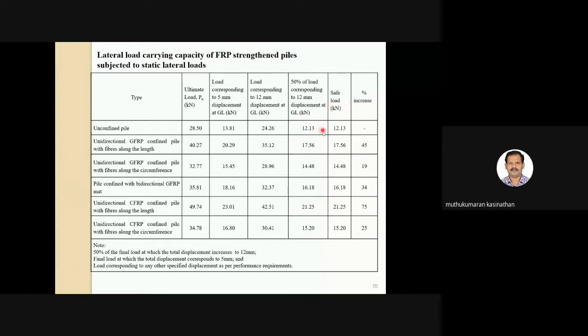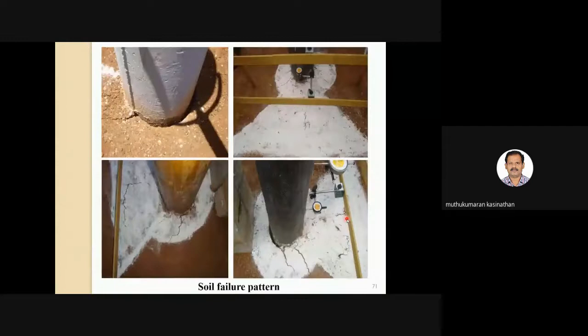So accordingly, the pile capacity has been estimated. So you can see here the variation of increment in the pile capacity, irrespective of the type of FRP. Minimum, you are getting almost close to 20% enhancement if you are using carbon fiber with the parallel arrangement. With the perpendicular arrangement, that is the longitudinal arrangement, you are able to get as much as 75% improvement in the capacity.